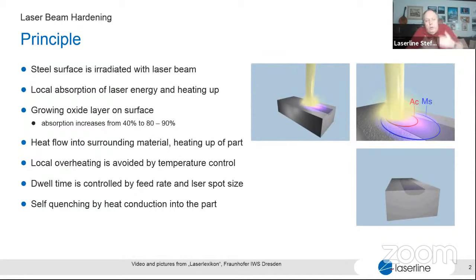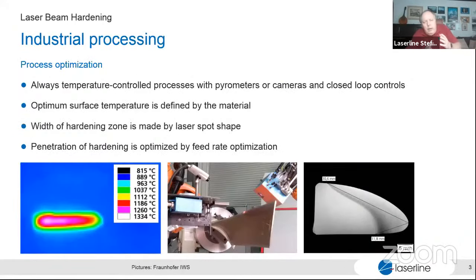And even the temperature measuring of the process is highly efficient, because any pyrometer or camera-based system can measure these high temperatures with high accuracy, with an emission coefficient of 0.8, 0.9. And so this heat treatment is a process that can be applied locally, highly efficient, and with low distortion at the end. And it is always running, we heard this topic today, as a closed loop process. We always measure surface temperatures with pyrometers or camera-based systems, and we give the signal to the laser power to keep the surface temperature constant in a closed loop by controlling laser power.